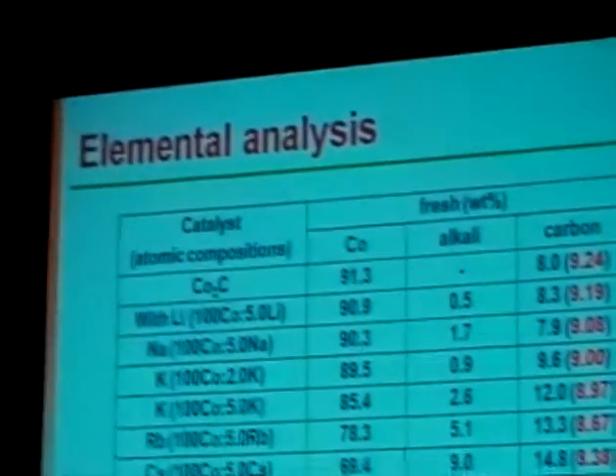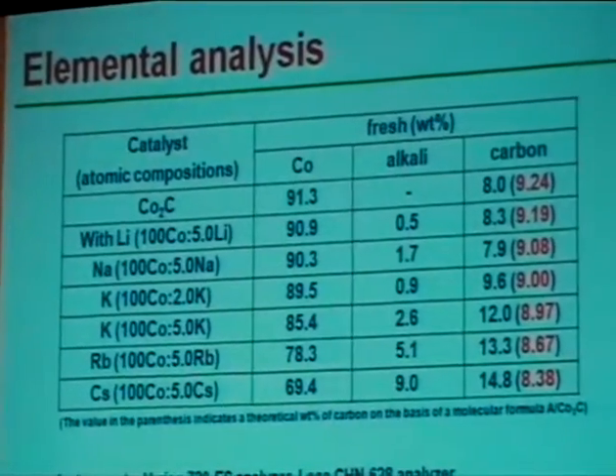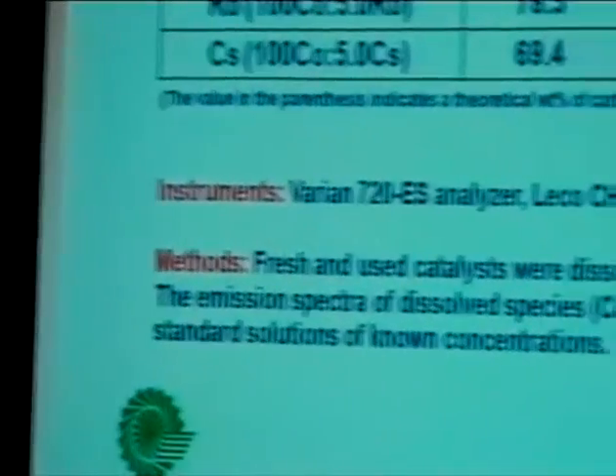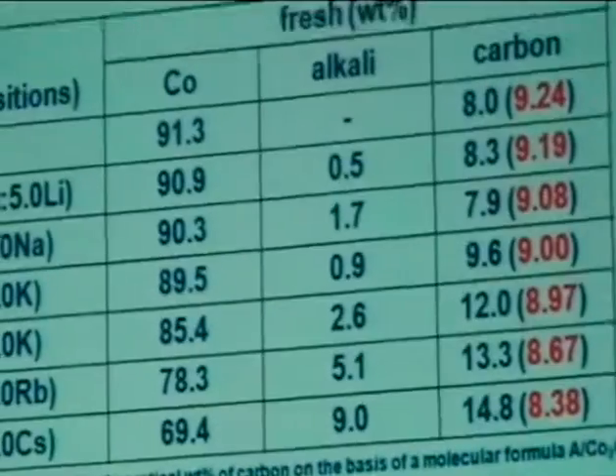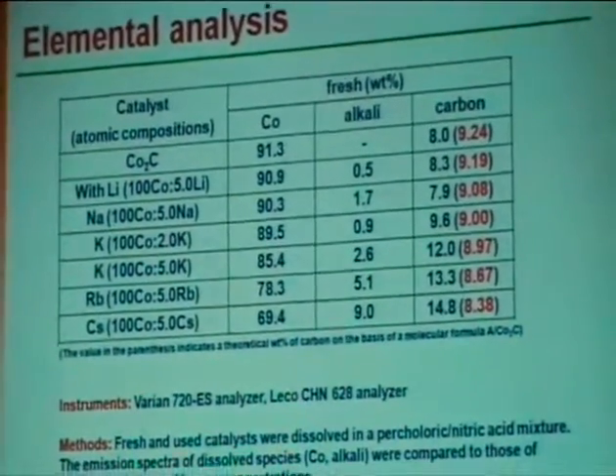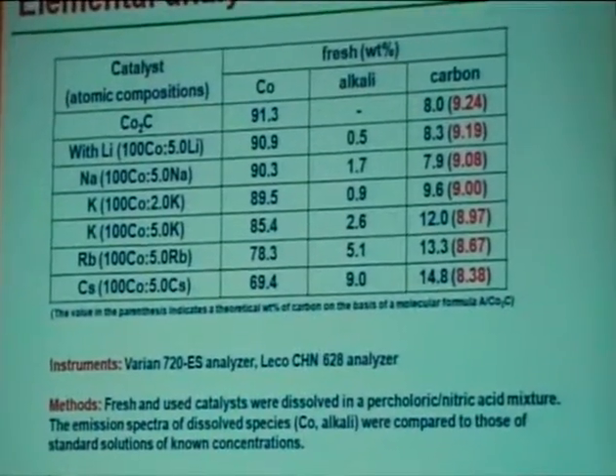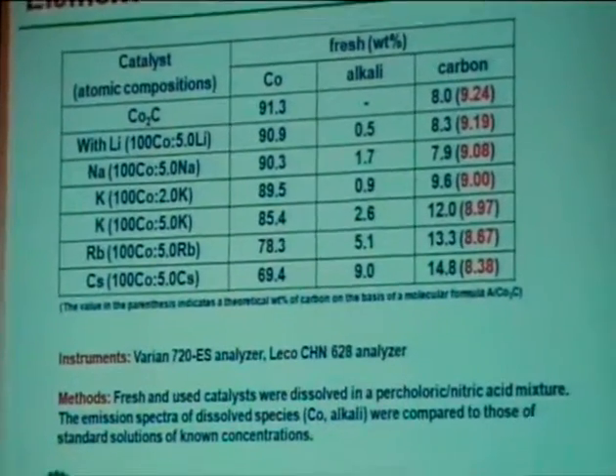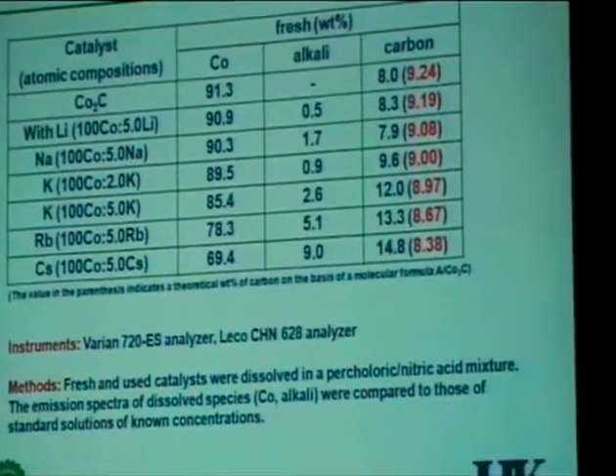And we did an elemental analysis on fresh catalyst, of course, after carbonation. The carbon content of the catalyst, as you see, as we go down the group, from lithium to cesium, increases. The values in the bracket show the theoretical weight percent of carbon on the basis of cobalt carbide, with the formula Co2C. So the carbon content was calculated based on this formula, and you can see that the value keeps dropping because of the increasing atomic weight of the alkalis.